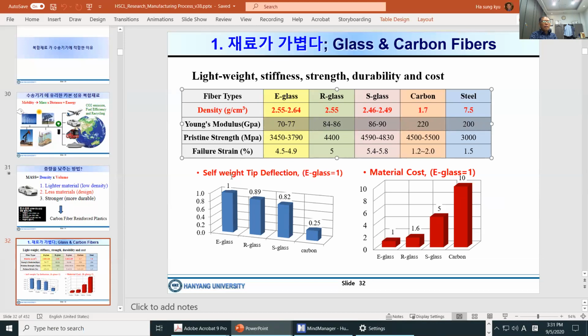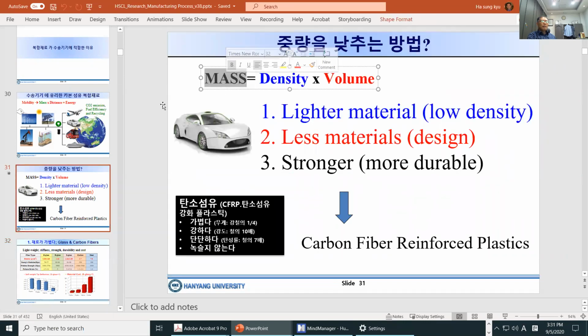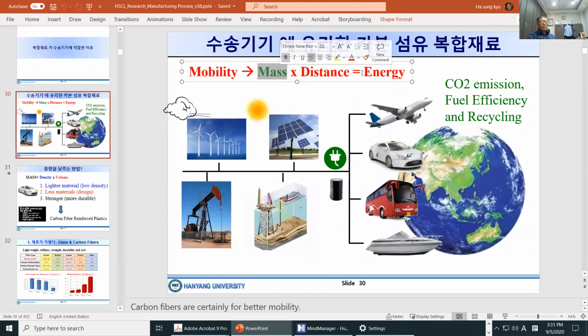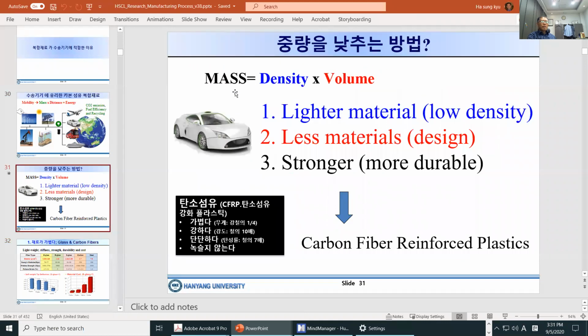Considering the self-weight tip deflection with E-glass equal to 1, the other materials have much less deflection. And material cost-wise, this is important, carbon is about 10 times higher than E-glass. Very, very expensive. Anyhow, the point here is the material is very light compared to steel. So back to here, why reduce mass? Reducing mass is to save energy. So to reduce mass, we need to use low density.